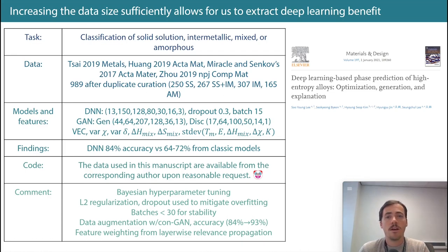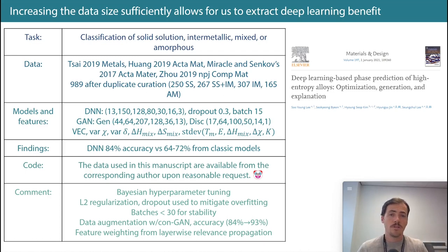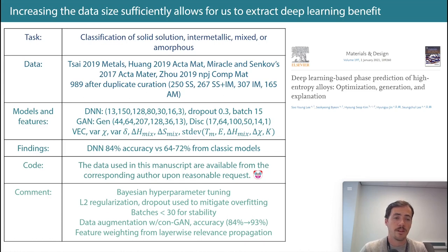They used data from a couple different sources and had 989 data points after duplicate curation, breaking down into 250 solid solution, 267 mixed, 307 intermetallics, and 165 amorphous. So a slightly harder problem — four categories — but more data. At around 1,000 data points, deep learning approaches start to make a little more sense.